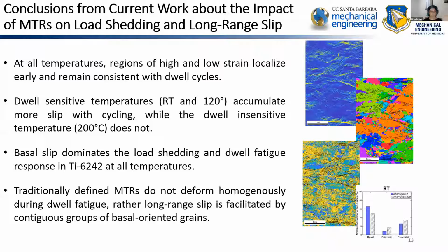There we go. Just the conclusions are that we know that it's a microstructurally driven process by the fact that we see those high and low strain regions that initiate early. We know that we have more strain happening at dwell sensitive temperatures than at dwell insensitive temperatures, and that's indicative of what temperatures are important for load shedding. Our basal slip is dominating, and the location and range of those basal oriented grains are the features that we need to consider whenever we're modeling and determining what's going to limit our dwell fatigue lifetime in these components. And with that, I would like to say thank you and open the floor for questions.